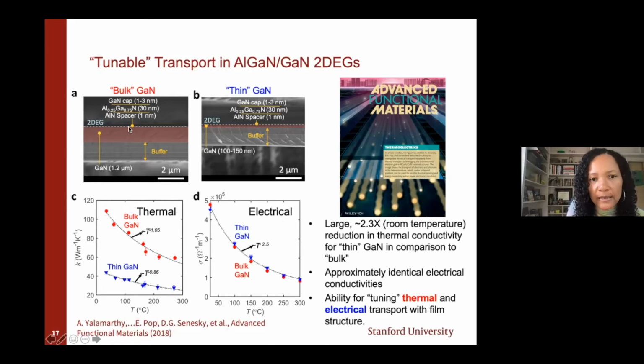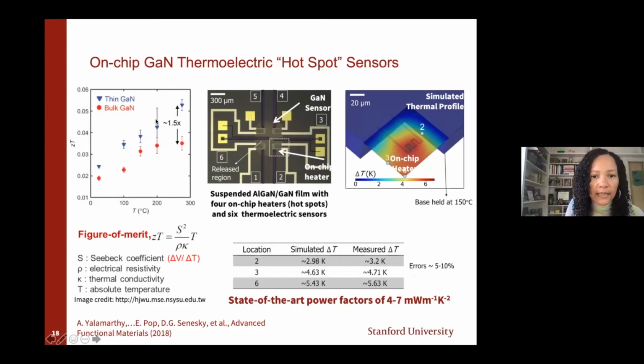So what we found is if we can change the bulk GaN, or the gallium nitride layer, which has high thermal conductivity, and we make it to a thinner gallium nitride layer, we can introduce more scattering effects and actually reduce the thermal conductivity. But at the same time, because of the 2D nature of the 2DEG, we can maintain the electrical conductivity. So we can think of this as tuning the thermal transport and maintaining the electrical transport in this heterostructure. So this is measured ZT coefficient, room temperature up to around 300 degrees Celsius. So we can see an increase in the ZT using the thin GaN architecture.